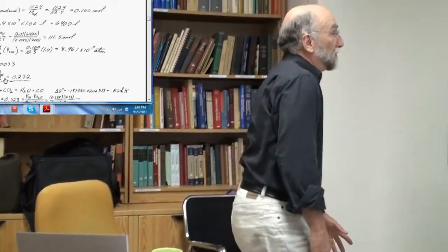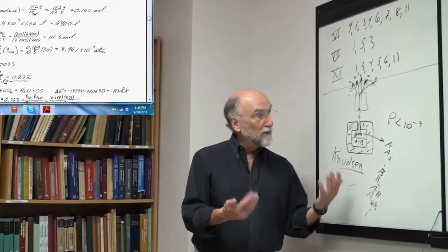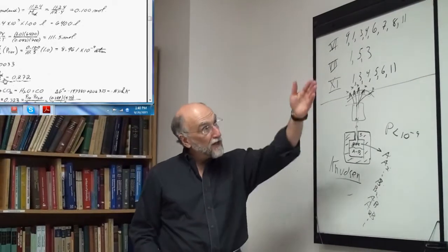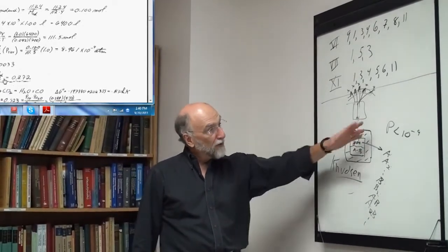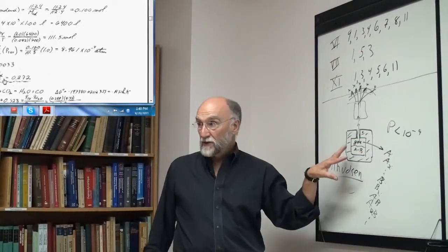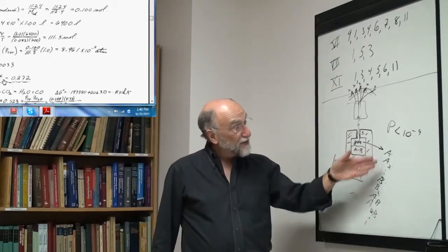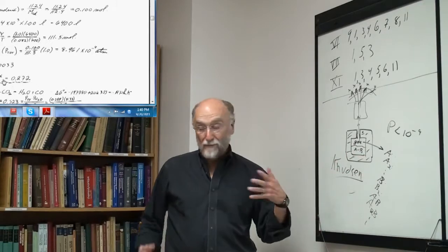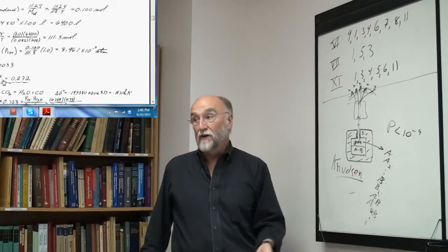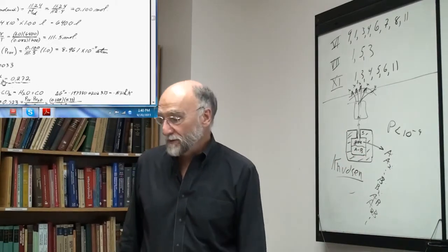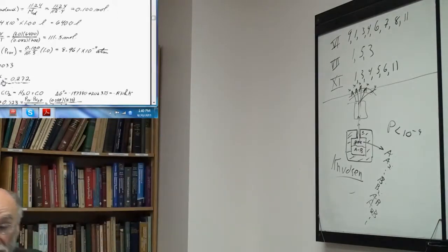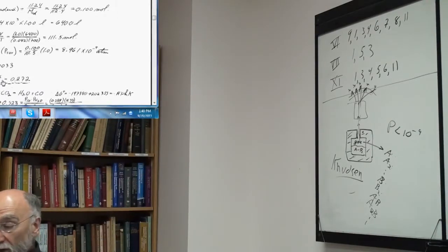Okay, so really, if you want to measure the partial pressures, at high pressure you measure directly. At lower pressures, 10 to the minus 3 and 10 to the minus 7, you can use the transport method. Below about 10 to the minus 9 or so, the Knudsen cell is used. The Knudsen cell obviates the necessity of assuming whether it's monatomic or diatomic; you find out what it is. You do a good measurement, and you measure all the activities simultaneously.